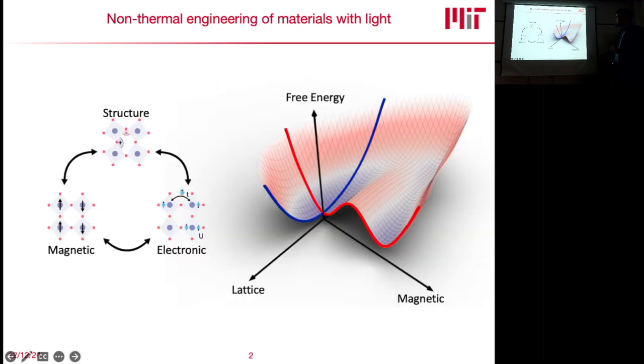And a more deterministic approach actually relies on so-called strongly correlated materials, where you have strong correlations and strong coupling between the structural degrees of freedom, so the lattice, electronic degrees of freedom, so electronic hopping and the on-site Coulomb repulsion, and also spin ordering, so spin interactions. And all of these are strongly coupled to one another, and this then leads to the fact that the free energy is now not only spanned along one coordinate, but along, in this cartoon, along two coordinates.